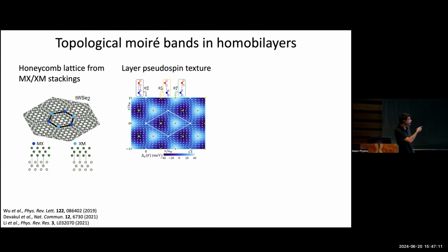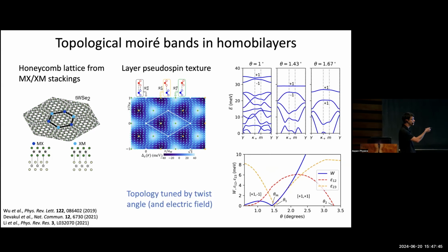So in certain homobilayers of transition metal dichalcogenides, what you find is that the details of Moiré stacking give rise to something that looks more like a honeycomb lattice rather than a triangular lattice. So there are local sites that are quasi-symmetric that have MX stacking, that is chalcogen above metal, or XM, that is metal above chalcogen. And if you look in real space, there's actually a winding number, a topological winding that happens associated with some layer pseudospin degree of freedom. And that topological winding gives rise to a Chern index for the associated bands of this homobilayer system.